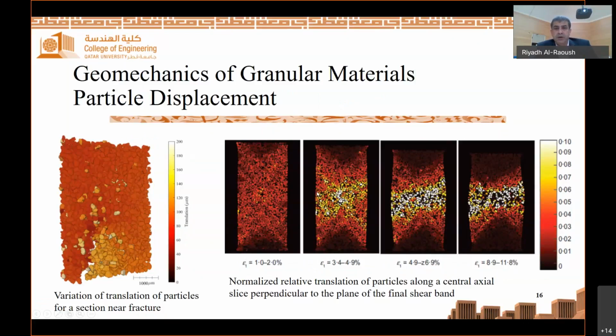We conducted experiments to investigate the stress-strain correlation and the impact on the particle displacement and evolution of the pore space. These are three-dimensional images obtained from computed tomography. These are real-time experiments, and we look at the increment of stress-strain at different times and different stress increments. And this gives us critical information for geotechnical engineering design and applications.